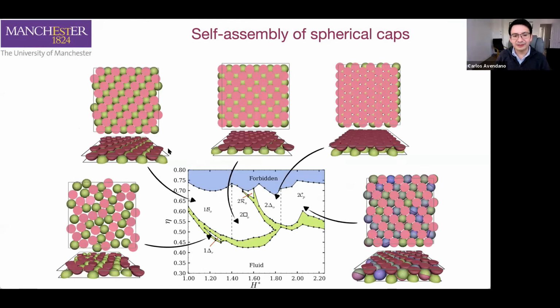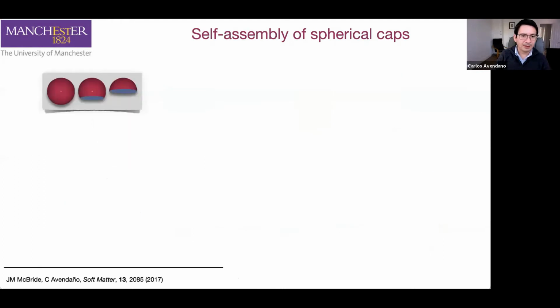The interesting thing is when you work only with half of the sphere, what we call the hemisphere, the monolayers are not observed anymore. And this system tends to jump from 2 layers to 4 layers and 6 layers, and it always goes in pairs. But again, this is the behavior that we can study with the computer simulations.